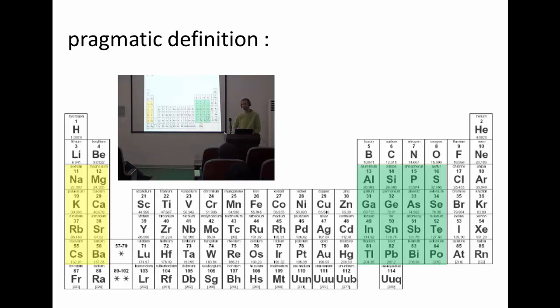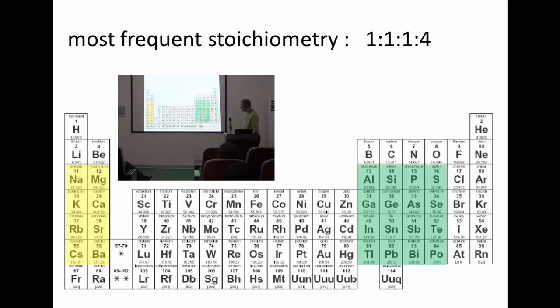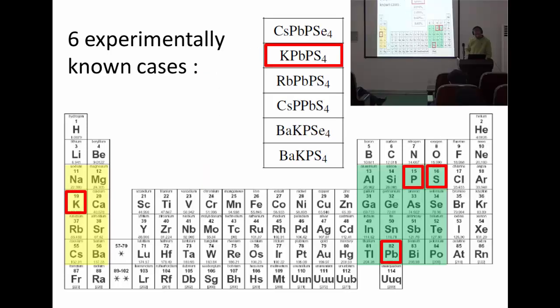If we look at these 200 existing quaternary Zintl phases, then you can notice that there is one stoichiometry that appears rather frequently, the 1114 stoichiometry. So let's take that one. Let's search for new Zintl phases that have that same 1114 stoichiometry. And within the 1114, there is one crystal structure that appears more often than others, and that's one with space group Pnma. There are six quaternary Zintl phases known with that stoichiometry and that crystal structure. You have all six of them listed there.